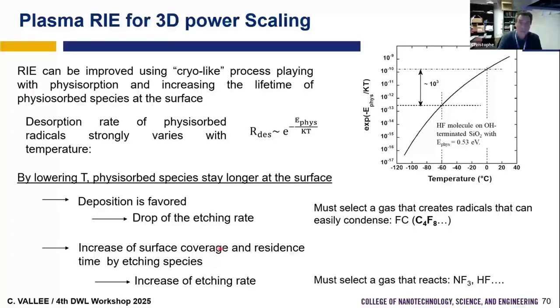So it's not good. But if you have some gas that will not do any condensation, that will only physisorb, and if you can have only 1 or 2 monolayers of physisorption, then the etching gas can stay longer at the surface. For example, if I take HF molecule, if you go from room temperature to -60, you will increase by 1,000 the lifetime of HF molecule at the surface. And if you increase the lifetime of this HF molecule, so etching gas, then when you add ions, you will increase the etching rate. So it's very nice.